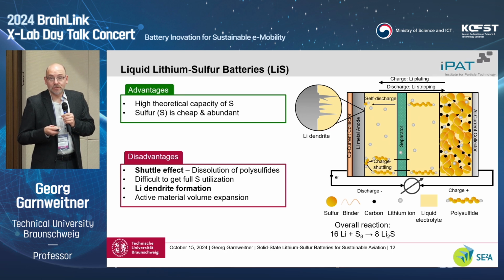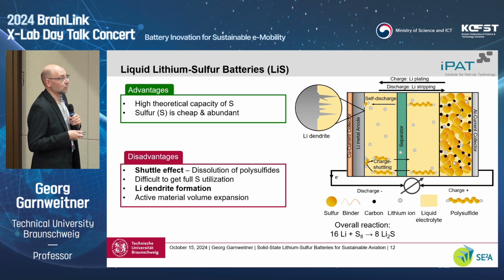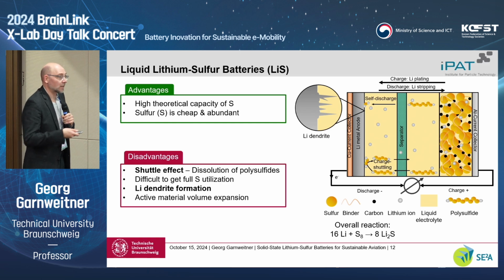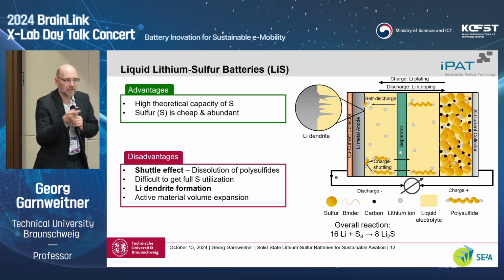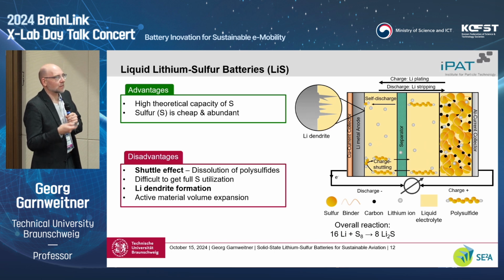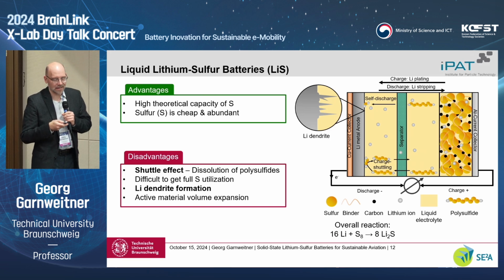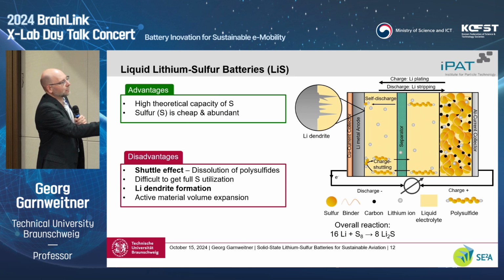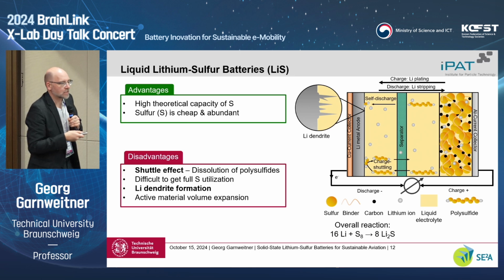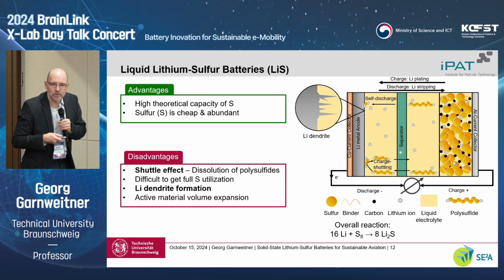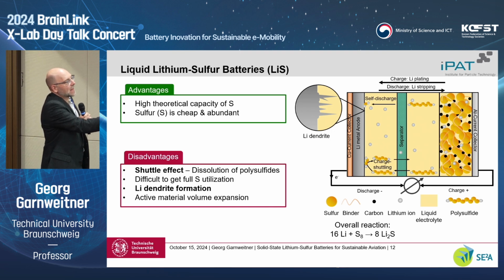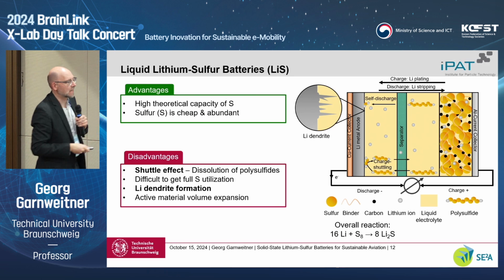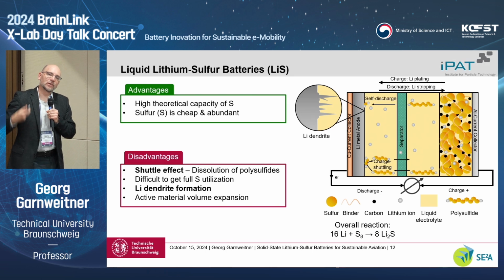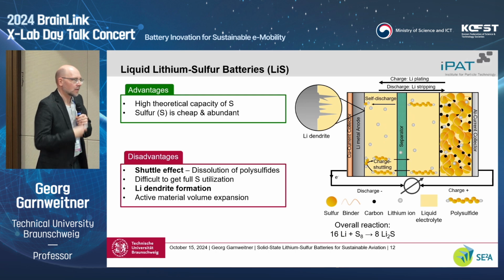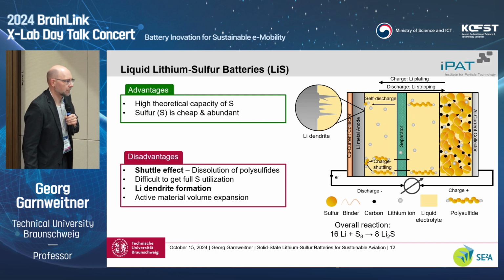But we have a number of disadvantages in a traditional lithium-sulfur battery with a liquid electrolyte. On the one hand, there is the dendrite formation on the lithium anode, as Mauro already mentioned, but we also have a so-called shuttle effect, because the sulfur has to react. It undergoes quite complex reactions, actually, and the so-called polysulfides, longer or shorter chain sulfur compounds that form during this cycle, they will reversibly go back and forth in the battery, and unfortunately they will deposit on the anode, form some insoluble compounds, and with this you lose capacity over the many charge and discharge cycles.